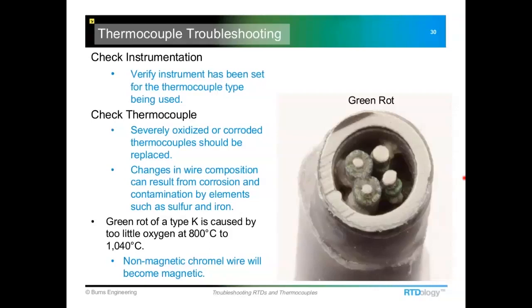Some of the symptoms of that: on a type K, neither one of the lead wires is real magnetic, but if this is happening, you'll notice that one of the wires is going to become much more magnetic than it normally would be. So it's kind of an interesting failure mode, actually, but it does happen, and you just need to be aware of it. Probably the easiest solution is just to go ahead and replace it. Thermocouples are pretty inexpensive, usually $30, $50 or so for one that's spring-loaded, goes in a thermal well type thing. So that's probably the easiest way to handle that.